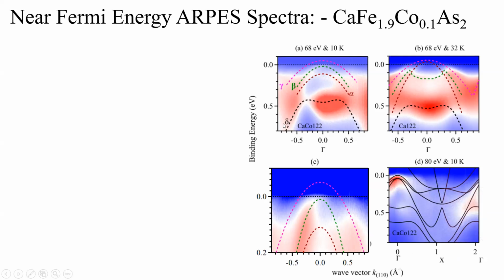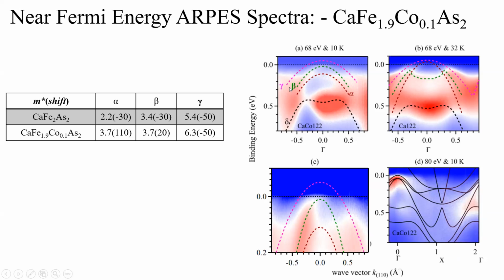So what I did is I drew these lines using the normal parabola equation, h cross k square by 2m, and from there I calculated the m star value. Since I know that the bands are almost parabolic close to the gamma point, I could draw these, and from there I calculated the m star value.